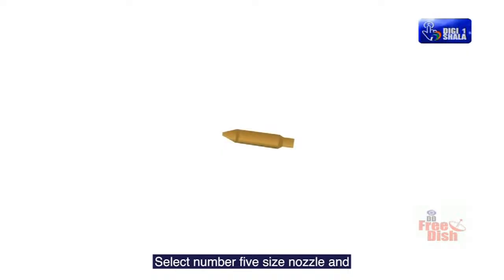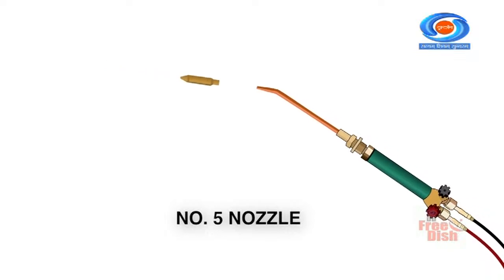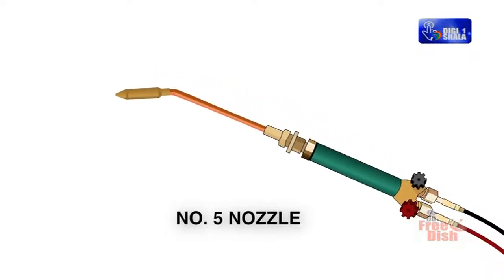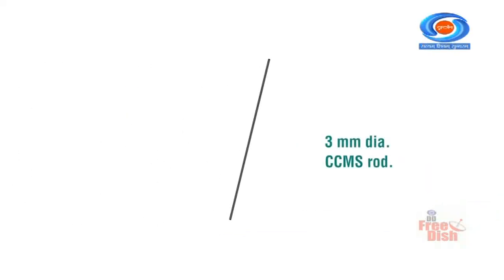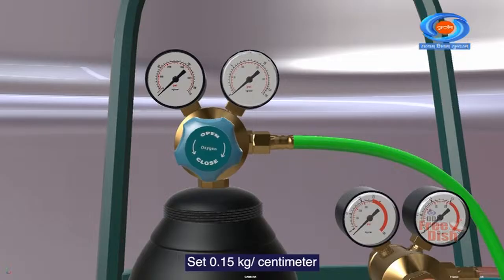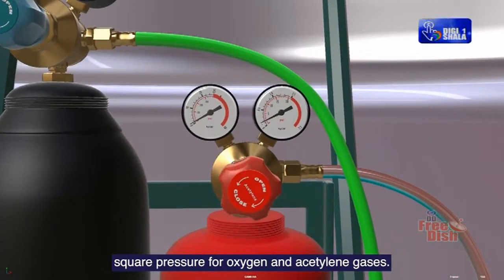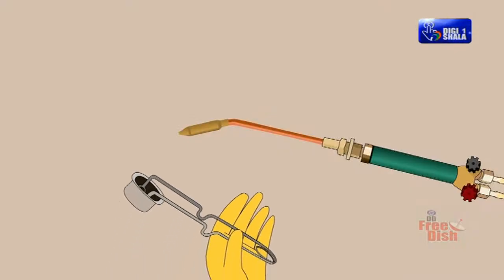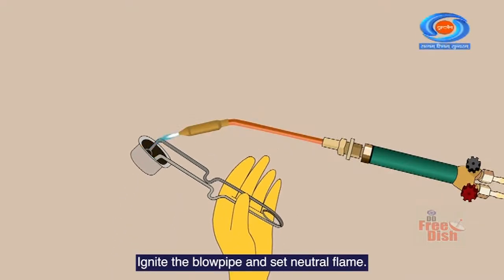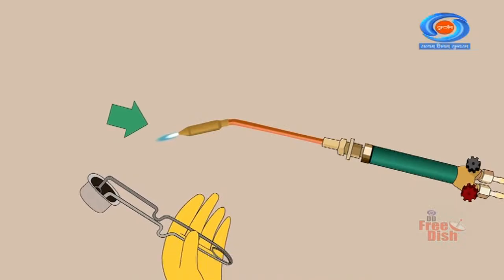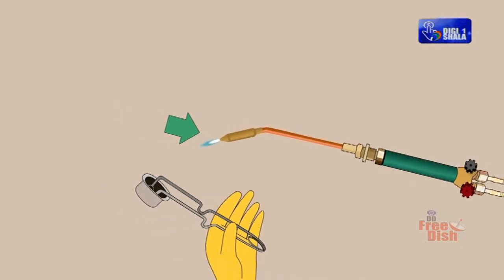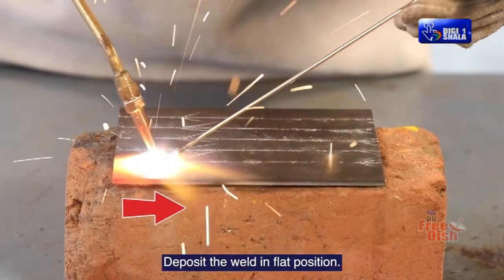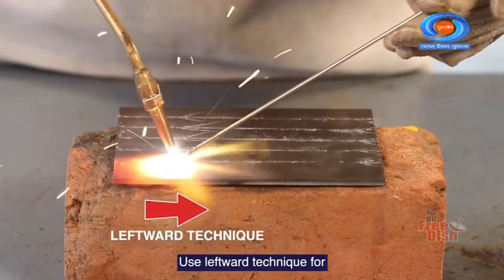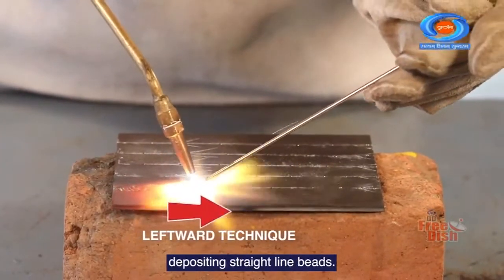Select number 5 size nozzle and fix it to the blowpipe. Select a 3 mm dia CCMS rod. Set 0.15 kg per centimeter square pressure for oxygen and acetylene gases. Ignite the blowpipe and set neutral flame. Deposit the weld in flat position. Use leftward technique for depositing straight line beads.